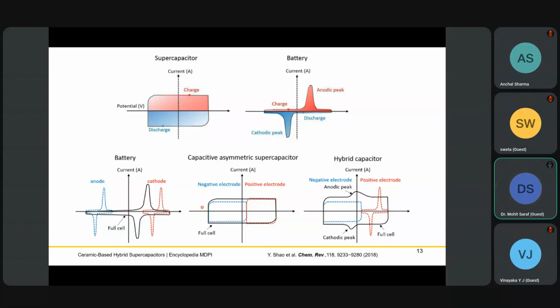But when you make this combination into a full cell, one is a negative electrode and one is a positive electrode, so you can enhance the energy. You can occupy the negative regime here and the positive regime here - this is like double layer capacitive material combined with another double layer capacitive material. So it's a classical example of an asymmetric supercapacitor, but both electrodes are capacitive.